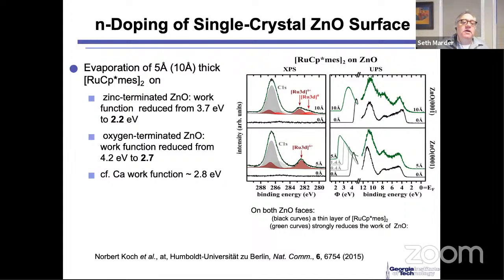So the first thing that I want to point out is that in this process, and you'll see why on the next slide, they examined the impact of N-doping of single crystal zinc oxide grown in ultra high vacuum. And what happened is they could actually determine, by virtue of how they grew this, whether it was zinc terminated zinc oxide or oxygen terminated zinc oxide. The work function of zinc terminated zinc oxide in UHV is 3.7. And the work function dropped to 2.2 electron volts.